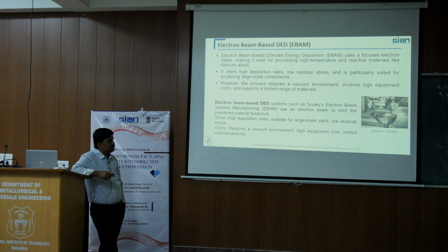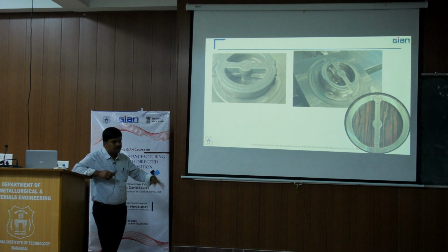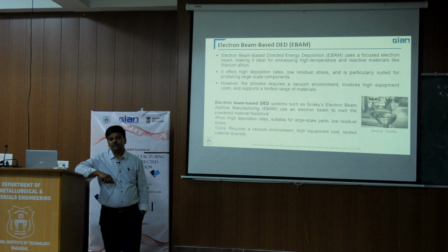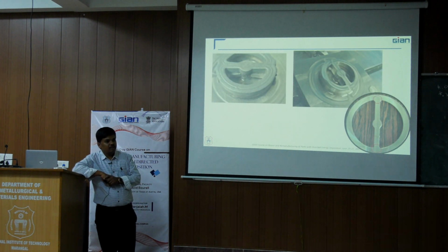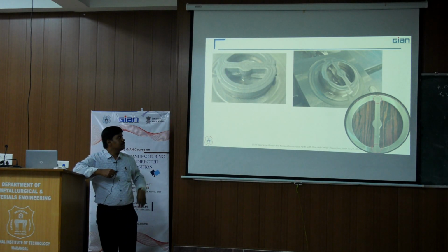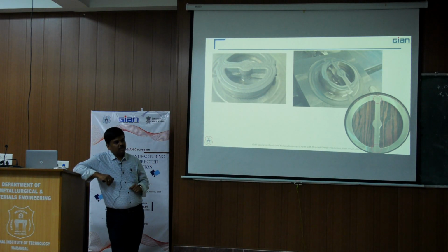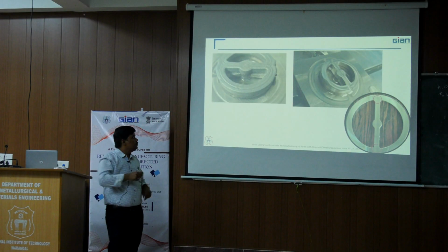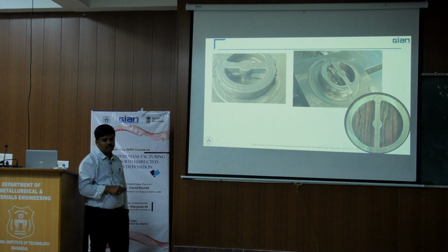Sciaky has made this, and we can see the differences between the laser DED process and the electron beam process. See the quality and the finish we are getting, and the surface oxidation, whether you maintain an argon atmosphere or use open atmosphere conditions. As this is stainless steel, we have done it in open atmospheric conditions with nitrogen as a protective gas.